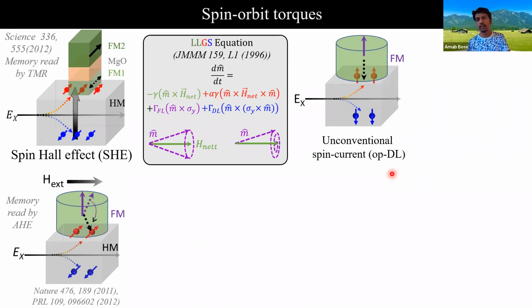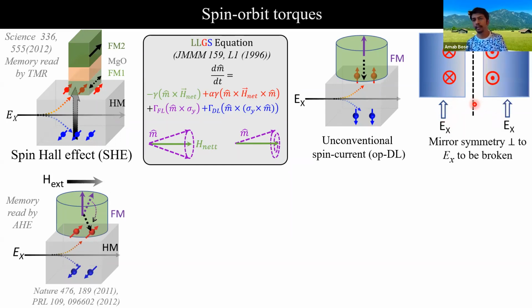Now, naturally, the question is, in what materials do we expect this sort of extraordinary spin current? Let's consider this case. Let's assume that when we apply in-plane electric current in this material, it produces out-of-plane spins. Now, upon taking the mirror reflection, we see that the generated spins flip polarity because spin is a pseudo-vector. That means it will naturally not be possible in most polycrystalline materials. So it would be allowed in various single crystal materials when we have mirror symmetry broken perpendicular to the direction of the applied electric current.